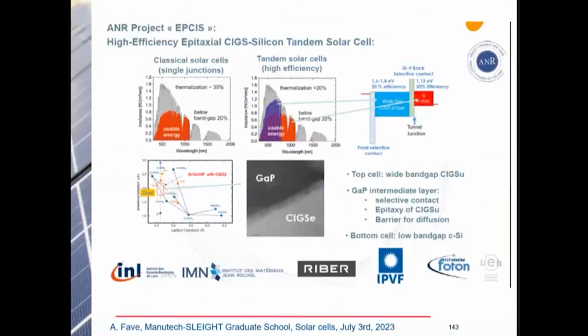Another possibility is CIGS. It's difficult to deposit CIGS directly on top of silicon, so we need some interfaces. One we are studying is gallium phosphide, a very thin gallium phosphide, in collaboration with people in Rennes, at the Photon Laboratory. You can see that we have very nice crystalline copper, indium, gallium, selenium, or sulfur on gallium phosphide, but still some trouble in the integration of all this on the bottom silicon solar cell.